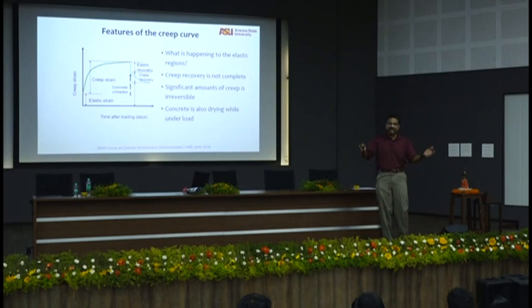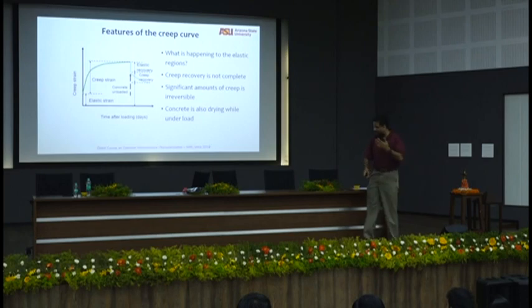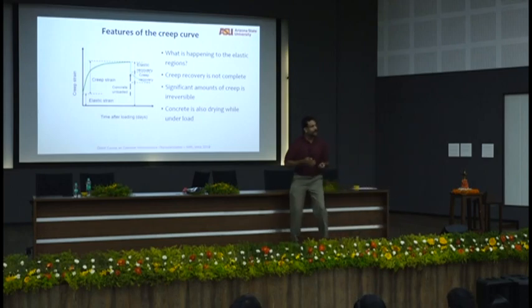Your measured creep of concrete will be lower because you are measuring the bulk part, but the actual response is dictated by the cement paste. If creep is a function of loss of water, your aggregates have no role in it, right? So overall measurement of creep, that's another thing that you have to be very careful. When you do these bulk overall measurements, you can tweak it whichever way it is.